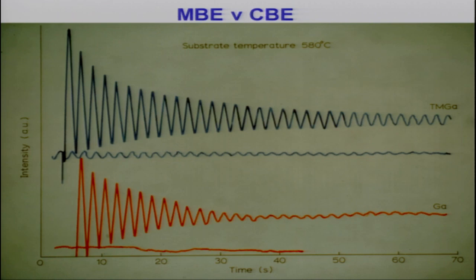One of the things that is curious is that if you look at a typical MBE RHEED oscillation, it dies after, in this case, about 35 seconds. You can prolong it by adjusting the conditions. But under the same conditions, the RHEED oscillations for CBE go on forever. So there's something curious going on here that we still don't understand. So there is mileage in MBE in the future. That's what I want to say. There's lots more to do.